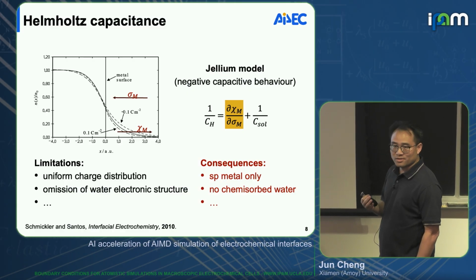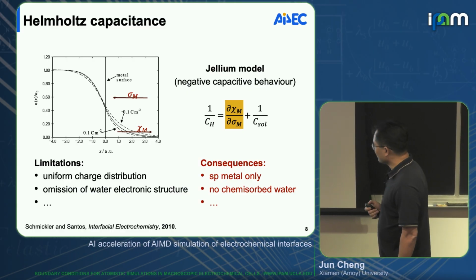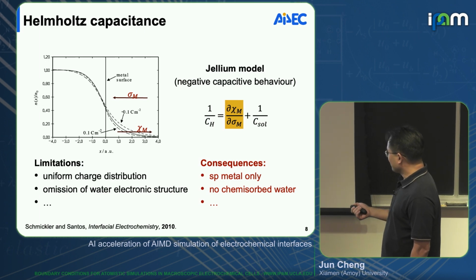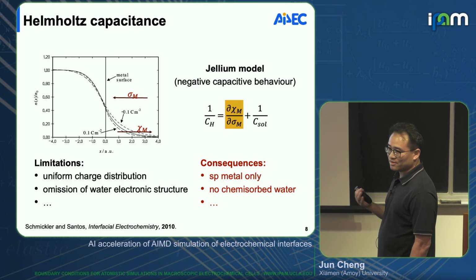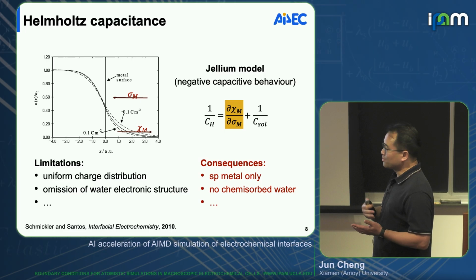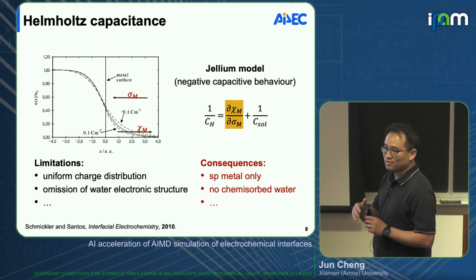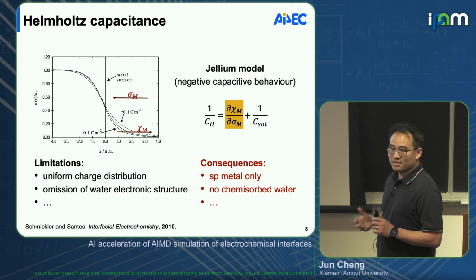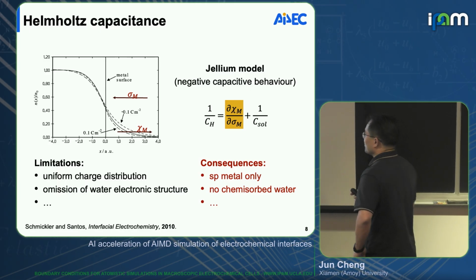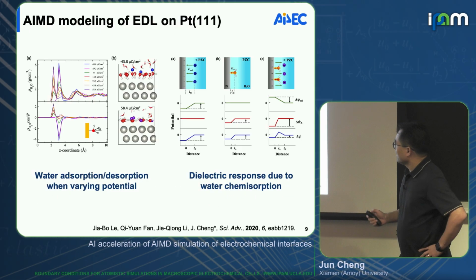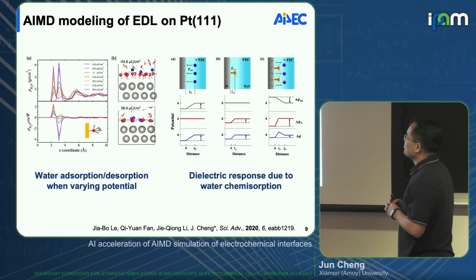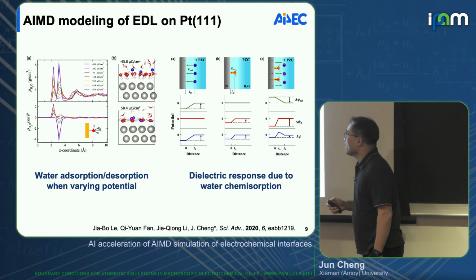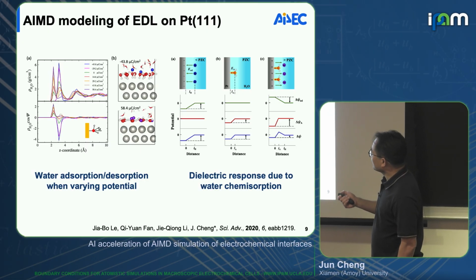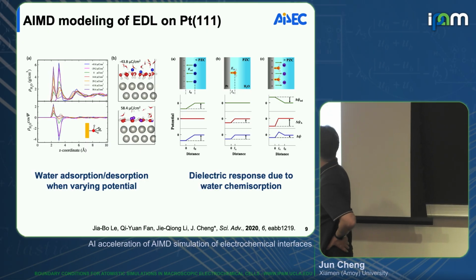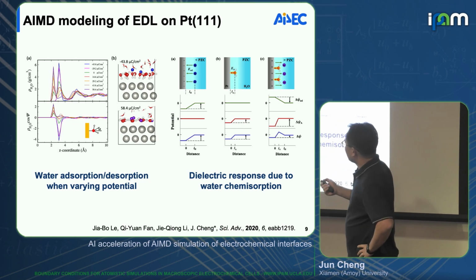Many of the transition metals are good electrocatalysts, like platinum, right? We also think of catalysis, you think of chemisorption, where you have species or reactants chemisorbed on the surface, that are all interacting with the rather localized d band, right? So that's certainly important to understand this effect. So we set up an ab initio molecular dynamics model on platinum. So just quickly show the result here. It's a really standard trick we use.